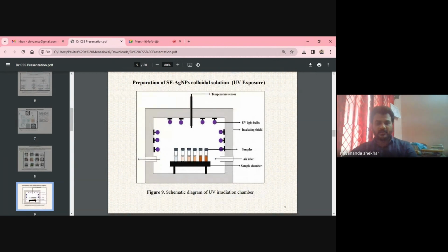Now, we take a fixed weight percent of silk fibroin solution, for example, 5 to 8% silk fibroin solution. We add a constant, fixed, known amount of silver nitrate to the silk fibroin solution. We made it like this: this is a pure silk fibroin solution, and this is silk fibroin with a fixed amount of silver nitrate, which we exposed to ultraviolet radiation. This is the UV chamber, and we kept all the bottles in the UV chamber. The color of the solution gradually changes from yellow to dark brown. This is the formation of silver nanoparticles in the silk fibroin solution.